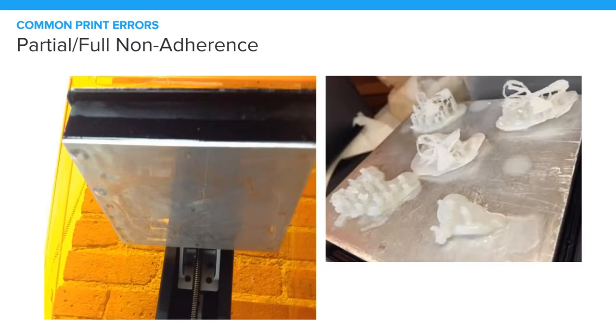So lastly, partial or complete non-adherence is mostly something that occurred with the Form 1 or 1+, but it can still occasionally come up with a Form 2. If you have a dirty optical window, and you've tried a different tank and it's still not working, then the tank might have a PDMS layer that's slightly out of whack. So basically, double check the cleanliness of your tank, your optic windows, all of those things.